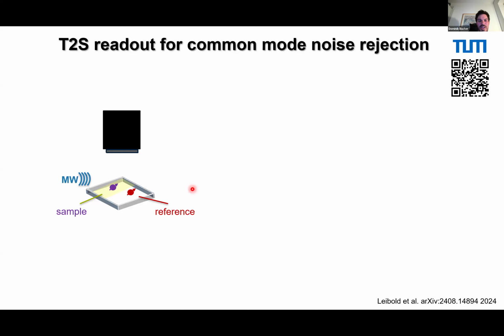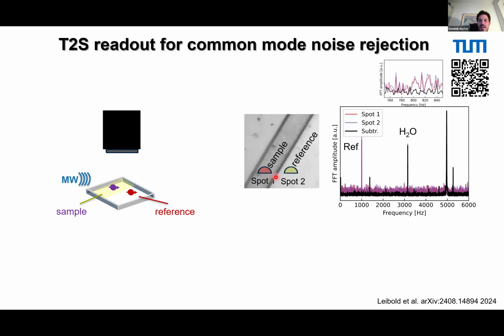but of course there might be many other possibilities to do that. So we basically would manipulate both spins. Both spins experience the same pulse sequence, the same sensing scheme, so they do the sensing at the same time. So all of the noise is encoded in both positions, and then we read them out one after each other. So what we get now is a signal, and we did this for NMR, but again, this could be any technique you can imagine, where we have one reference and one sample spot. So we get the NMR spectrum here and here, and again, the measurement was done at the same time. We just read out the reference at a different time, at a different position, at the end.